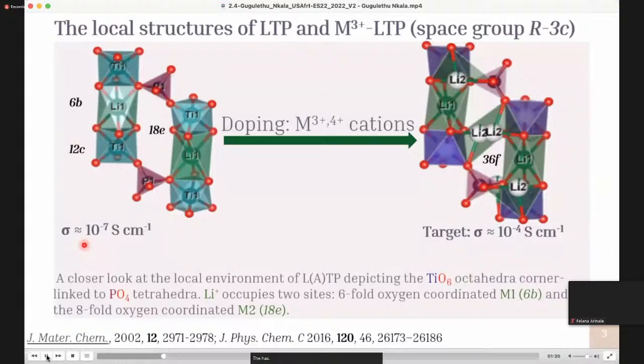The highest conductivity in NASICONs has been reported for 15% aluminium doped LTP, in the order of 10 to the negative 4 Siemens per centimeter. This is attributed to the tuning of the bottleneck size that allows for faster migration of lithium due to lower activation energies and increased bottleneck size, as well as increasing the amount of charge carriers. The increase in the amount of charge carriers is due to the excess lithium ions that are added for charge balance that then occupy the favorable 36F sites within the 18E cavity.